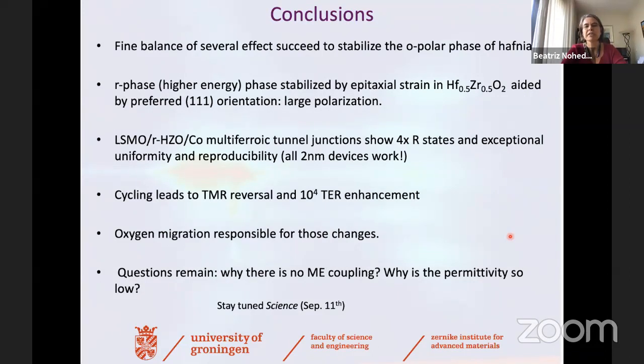You need enough oxidation, but as I said before, it could be that the rhombohedral phase requires a little bit of oxygen vacancies. We have not yet done the systematic study that we have done, for example, with nickelates or with other oxides, to investigate the exact values of polarization as a function of oxygen pressure. But I can say that to get the right phase, the exact oxygen pressure window is not so critical as for bismuth ferrite or for the nickelates.